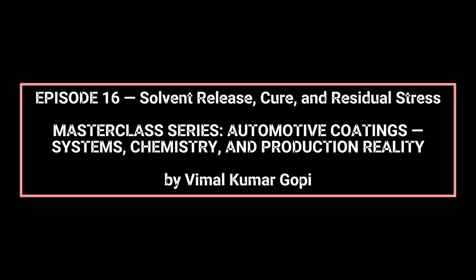OEM durability validation evaluates coatings under accelerated weathering, thermal cycling, chemical exposure, and mechanical stress. Residual stresses influence performance in each of these tests. Coatings engineered for robust solvent-cure balance maintain dimensional stability, adhesion, and appearance throughout their service life, even under fluctuating process conditions. From an RD&I perspective, designing coatings requires an integrated approach.